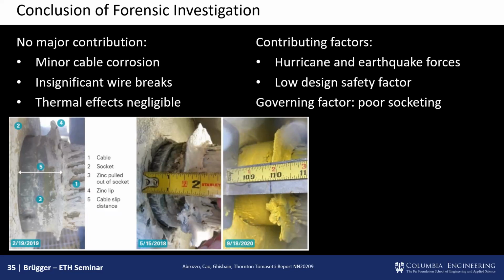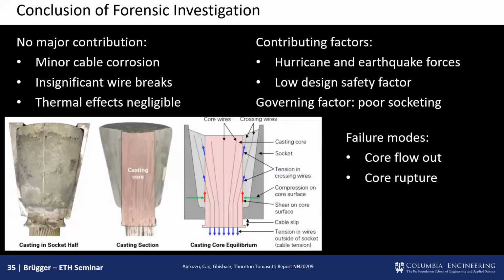This was cataloged and photographed, but nobody thought to actually act on it. So that's why we have the photos. They took photos, but they didn't do anything. So essentially, in the end, what happened was that because we don't have those wires actually spanning the entire socket volume, that truncated conical bore, then we don't have a hydrostatic stress field inside the zinc, but instead we have a highly deviatoric stress field with massive shear along those lines.